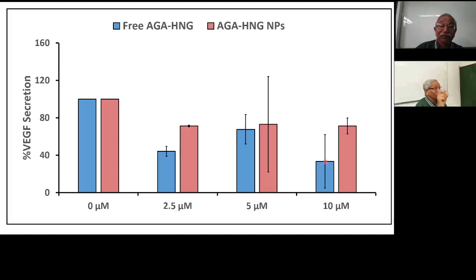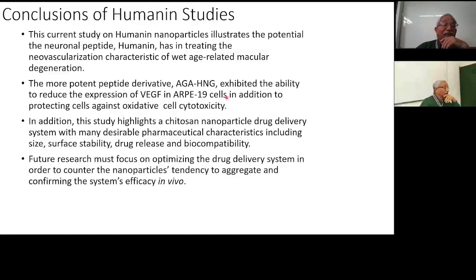With 10 micromolar, it was significantly down with free AGA-HNG. But with nanoparticles, we did not see a similar type of reduction. That means the AGA-HNG was not released as much as necessary. That's why we did not see that. So this was one observation. So the conclusions of the humanin study showed that this current study of humanin nanoparticles illustrates the potential of neuronal peptides.